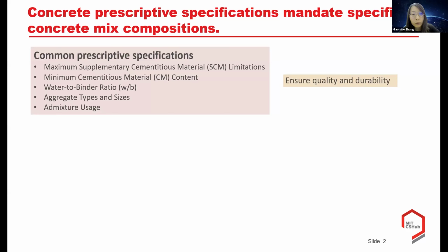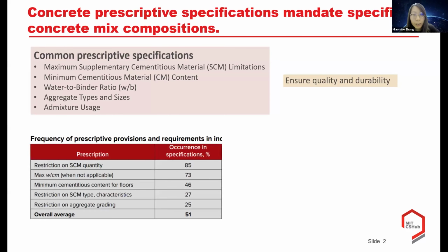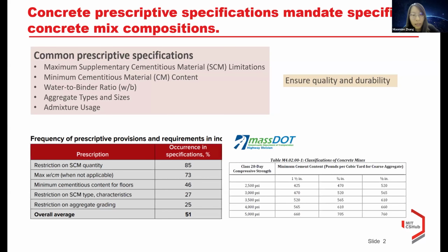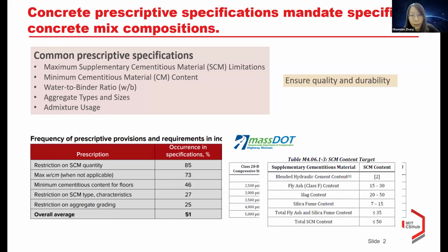Other parameters include water-to-binder ratio, aggregate types, maximum aggregate size, or admixture usage. Here are some examples of prescriptive specifications of concrete mixture. This table lists the high-ranking prescriptive specifications. This is a minimum cementitious material requirement from MassDOT and the SCM content requirement, which are different for different SCM types. These prescriptive specifications are designed to ensure the quality and durability of concrete products.